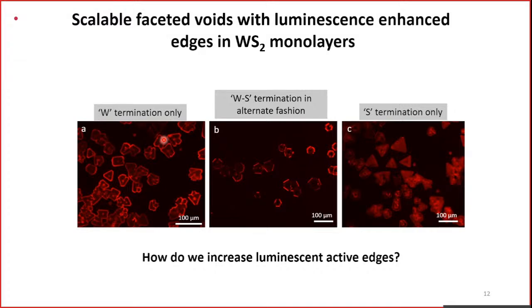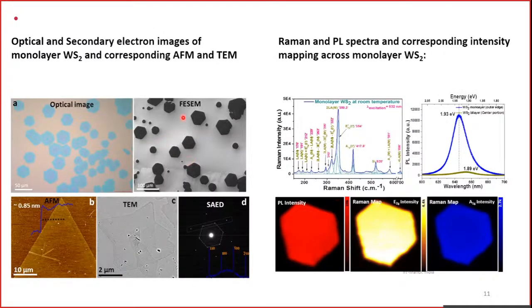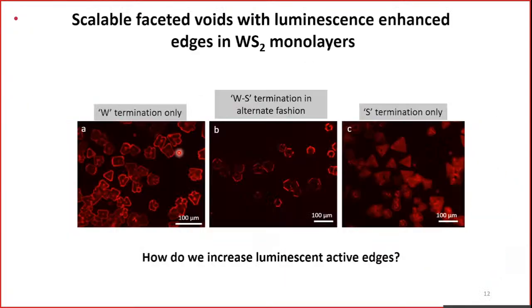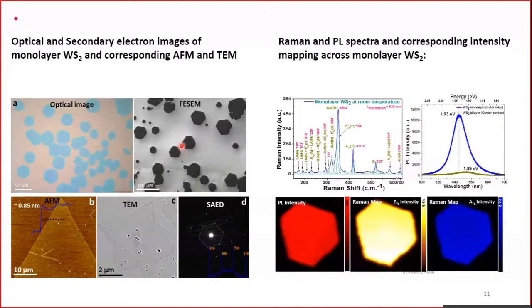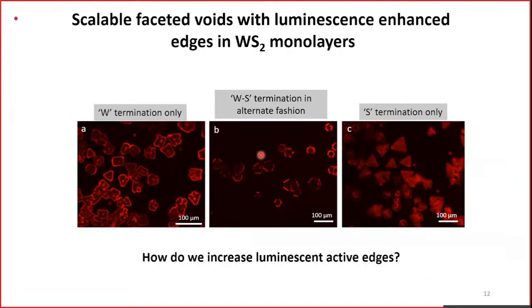I'll give you 3-4 cases where the manufacturing can be done in a controlled way towards enhancement of the property. In many cases, as shown here, you will have a triangle or truncated triangle, in some cases a perfect hexagon. When you have a perfect hexagon or truncated triangle, essentially we end up having 6 edges, right? The edges can have a different termination. It can have a tungsten termination, or a sulfur termination, or in some cases, you can have a tungsten termination in one edge and a sulfur termination in the other edge.